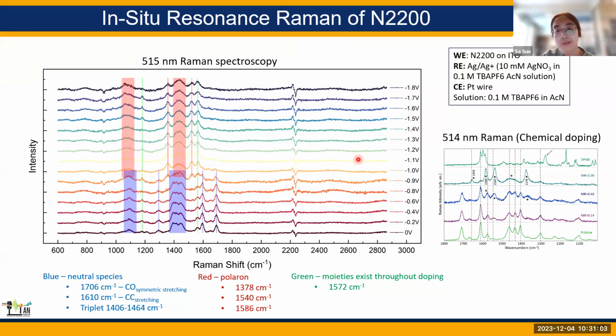This is also the stacked Raman spectra scanned from 0 to -1.8. We also saw similar features. For example, the blue shaded area shows the neutral N2200 peaks. We can see that it decreases after the reduction of N2200 happens. Meanwhile, in these four red shaded areas, new features appear upon electrical doping. These four bands are actually aligned with what the previous literature saw from chemical doping. So now the electrical doping and chemical doping show a similar trend in the vibrational information.